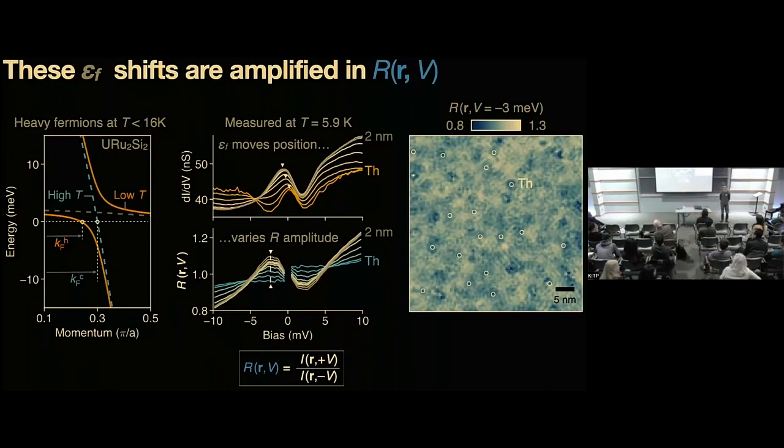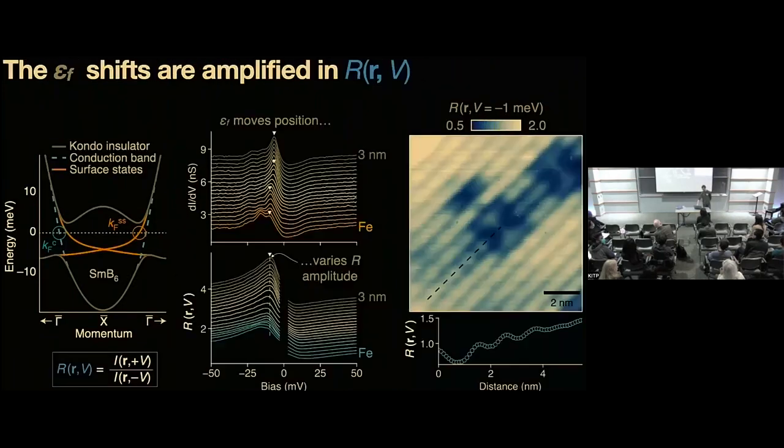Hi, I have a question about length scales. The Kondo hole, which is just around an impurity, must be on a nanometer scale. And then what about the oscillations? When you are looking at the de Haas-van Alphen oscillations, that must be a much larger length scale. That's a really good question. The length scale that we see is a few nanometers for these puddles, yet the quantum oscillations have a cyclotron orbit with a radius of 100 nanometers. So they seem like very different things.